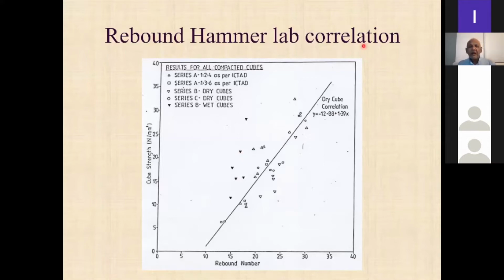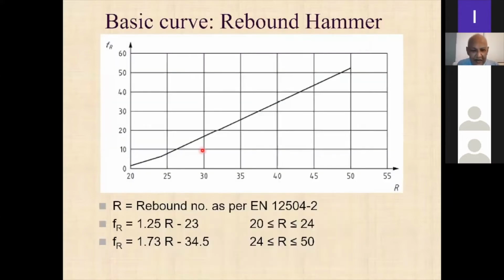Now, here you do in fact find a straight line, right? In the Eurocode, there's a slight change here, the inclination changes slightly. So what we are doing is, if we are getting a correlation between rebound number and strength, we have to get that correlation using 18 cubes, and we have to find the difference between each one of those points and this line, so that we draw a line that is parallel to this.